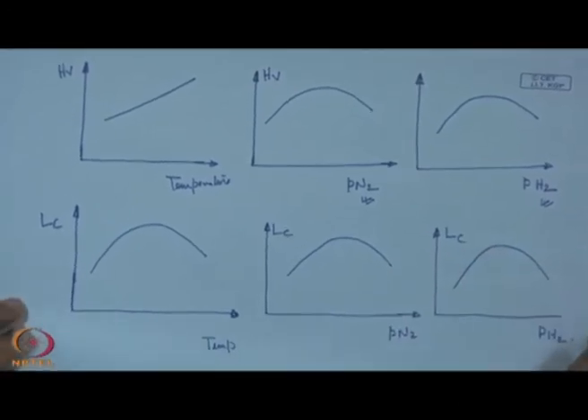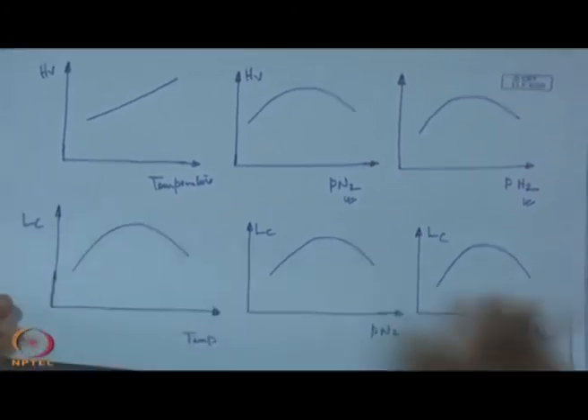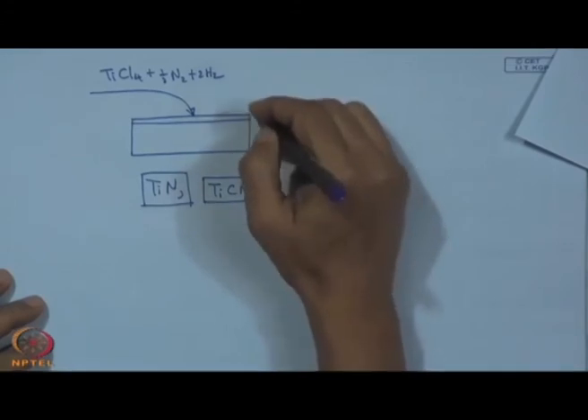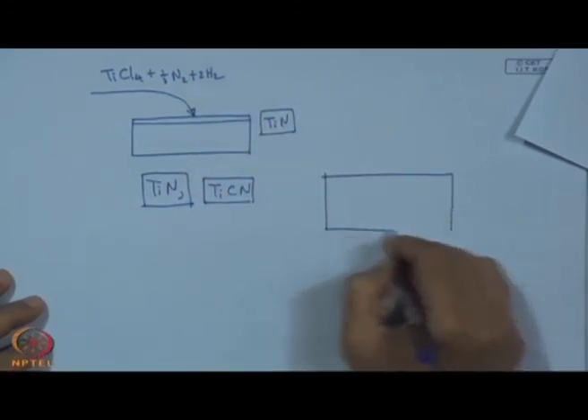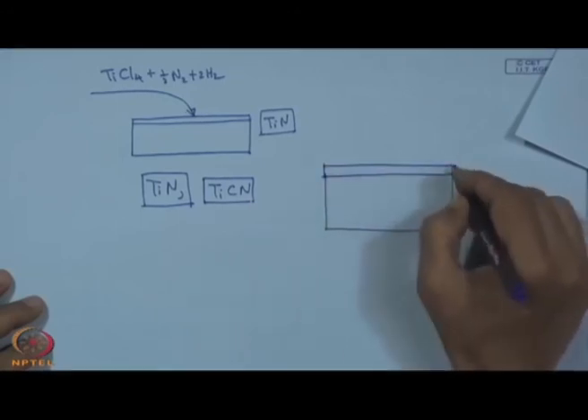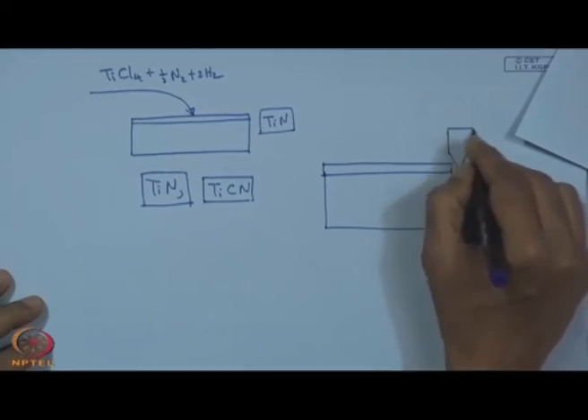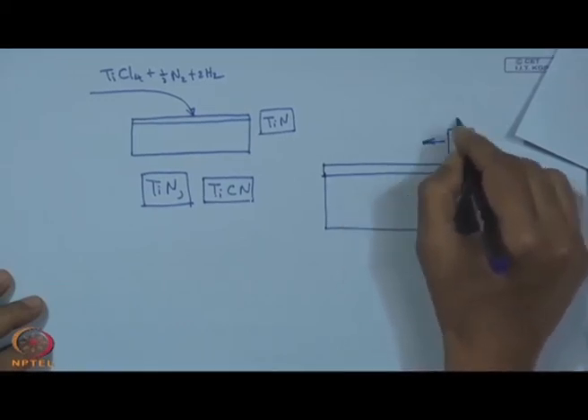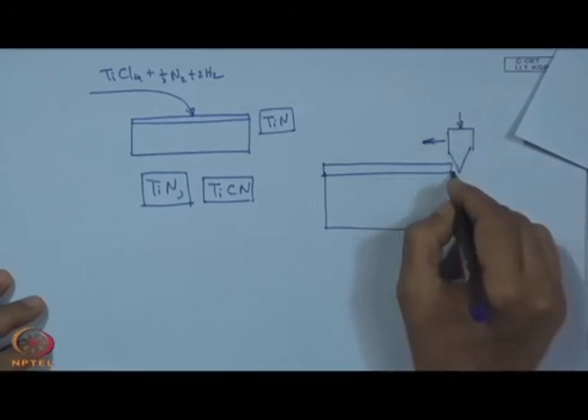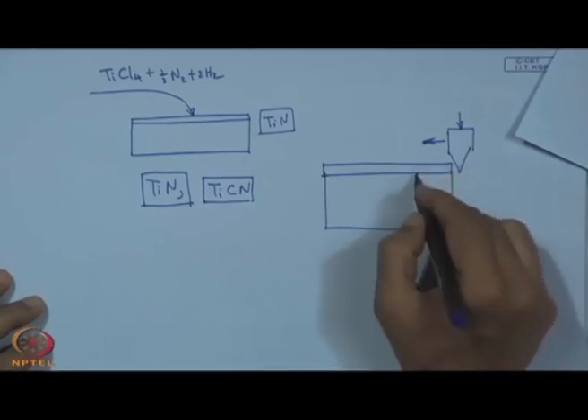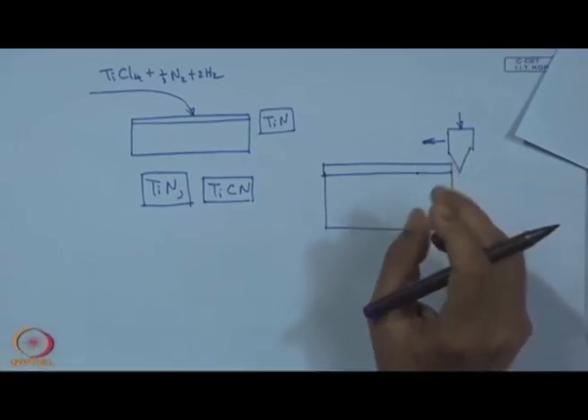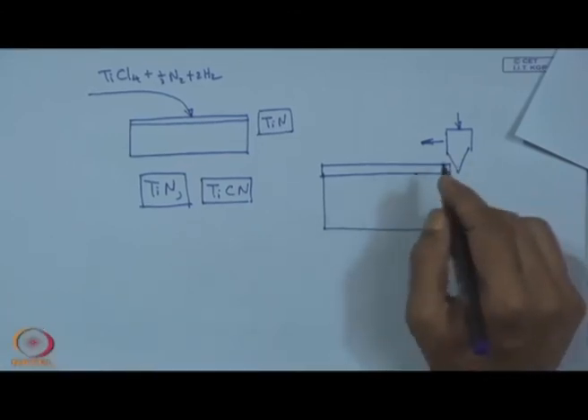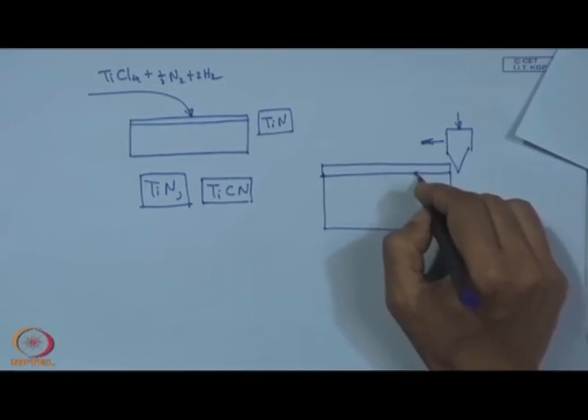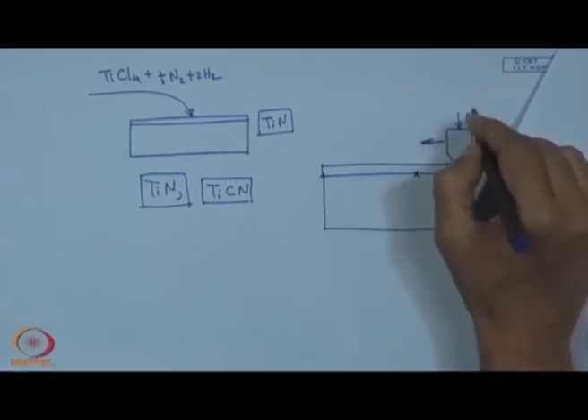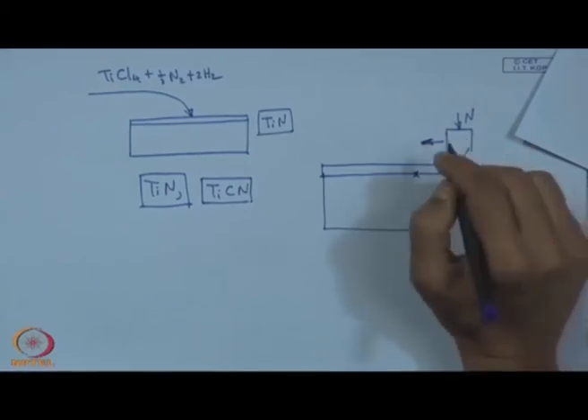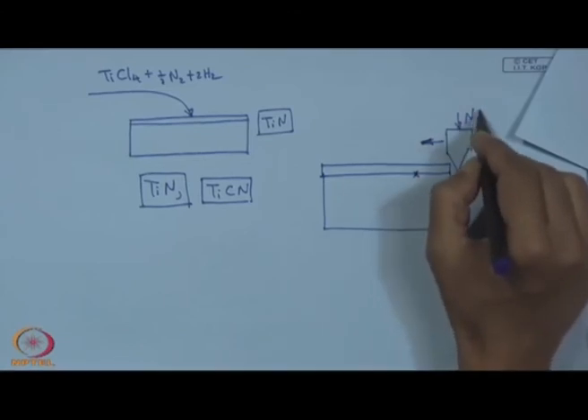That means, for all the cases, this critical load means, if it comes like this, this is the coating and there is a scratching tool which moves on this side and it has a penetration, and it is actually the load at which the first detachment is detected. For that we have a dedicated instrument, the adhesion scratch tester. This adhesion scratch tester detects the point corresponding to a normal load at which this first separation takes place, and that is known as the critical load, which is the normal load here.